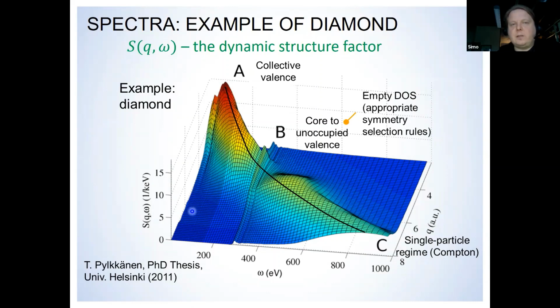And the spectra now are encoded here with red being high intensity, and the height of this pillar being the intensity as well. They depend on two variables. Because this is a scattering process, we have a momentum transfer Q, and then the energy transfer omega, because it's an inelastic scattering process. So they are represented here on these axes. We have the energy transfer in electron volts, and here the momentum transfer, in atomic units, meaning in terms of the inverse Bohr radius.